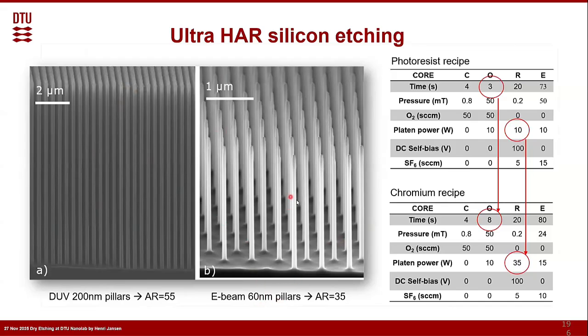And because we are using chromium as a mask, we can use the oxidation much longer. So instead of, let's say, for resist, we could not go that far because the retraction is so strong that our selectivity would be compromised. But for chromium, we can go to a much longer one to make sure that, when we have high aspect ratio structures, everything, even down to the very bottom, is strongly oxidized enough to get the self-limitation working perfectly.